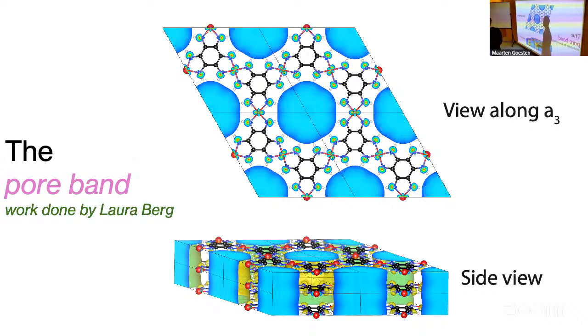Now this actually, we could think more about that, but it's very similar to what is seen with the interlayer band in graphite. So that one also takes off very steeply between gamma and A. And actually, what you can do is you can plot just the free electron dispersion. This has been calculated. There is a 2005 Nature Physics paper on graphite intercalate superconductors. There they calculate just the free electron dispersion. You will also see that it takes off much stronger than the normal molecular orbital-like levels. Okay. Free electron dispersion typically will be very strong.